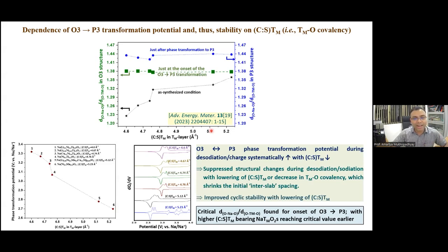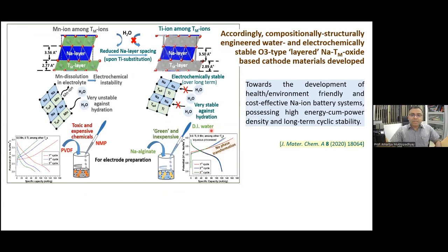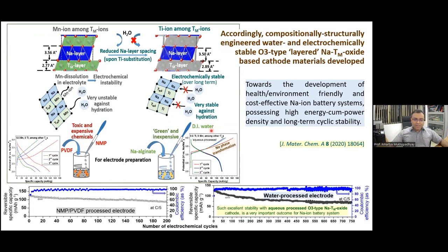So based on this idea, one can design multiple layered transition metal oxide cathode materials, some of which can be used in a practical sodium ion cell. So since we were able to make good materials which are water stable, for one such material we prepared aqueous processed electrodes.